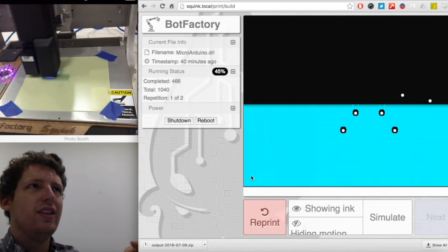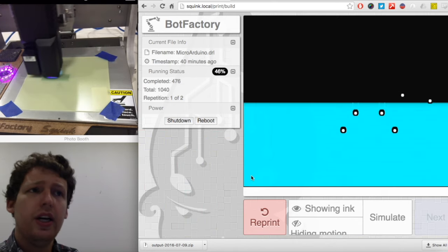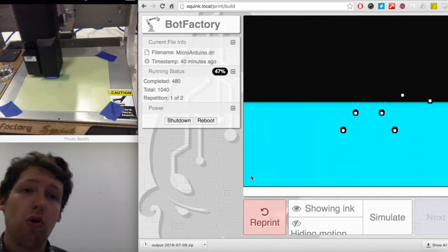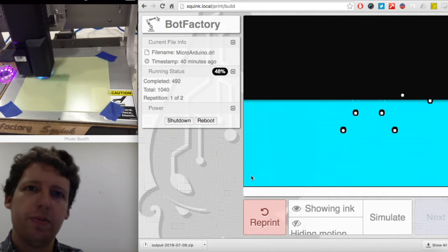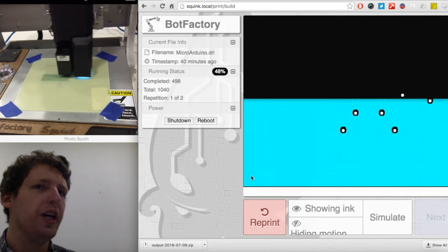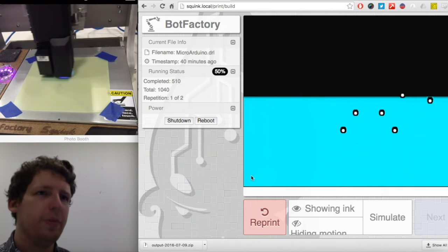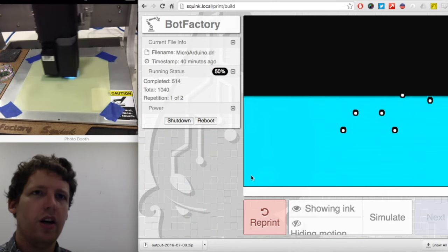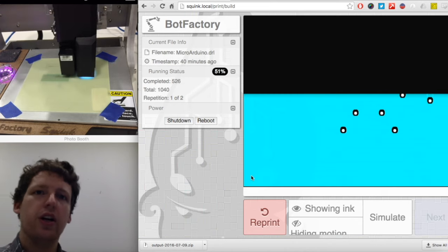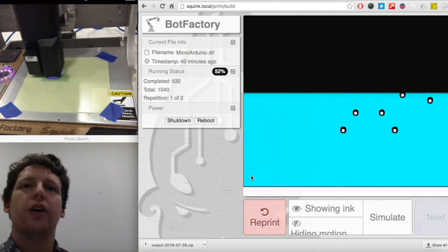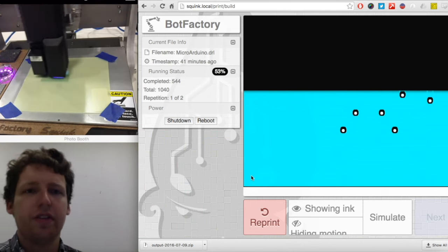But we find that if the insulating layer is not attached to the substrate or the preceding layer below it, around the trace, it's going to tend to pull off the conductive ink that you're printing over. It's partly because this material tends to warp and change a little bit as it's cured. So don't design a circuit board that has a minimal amount of insulating ink on the interleaving layers. You want to have large chunks of insulating layer so that the entire circuit is held down completely and the insulating ink doesn't pull off the circuit as it cures. So that's just one thing to worry about that we've been seeing a few times.